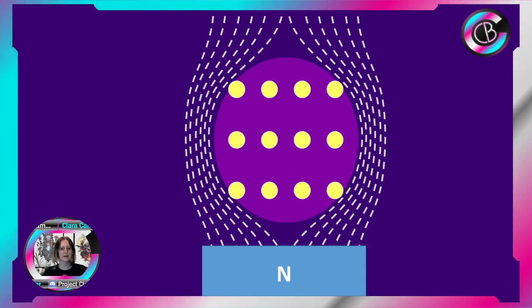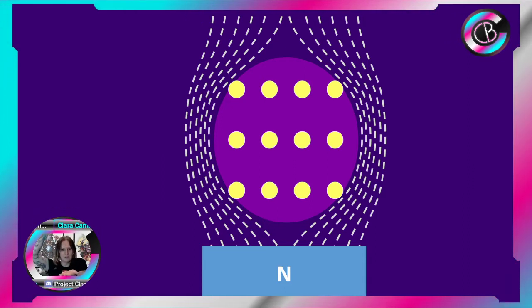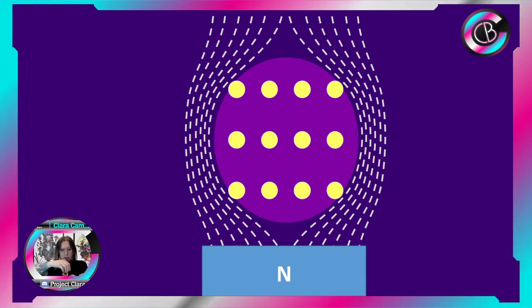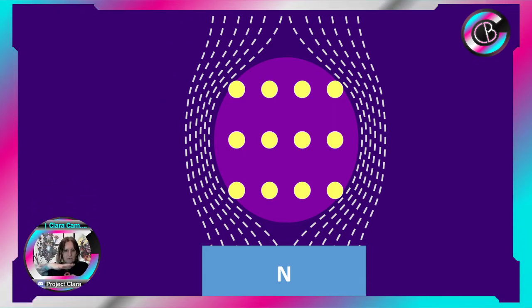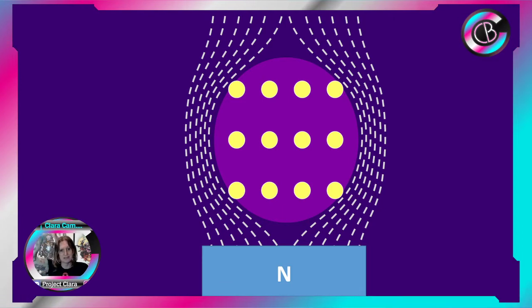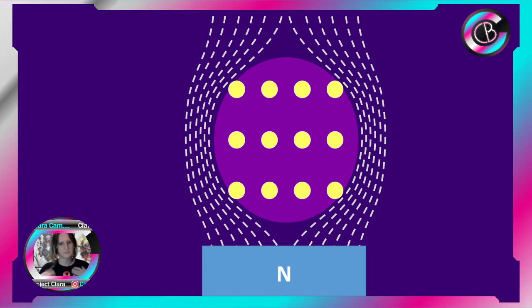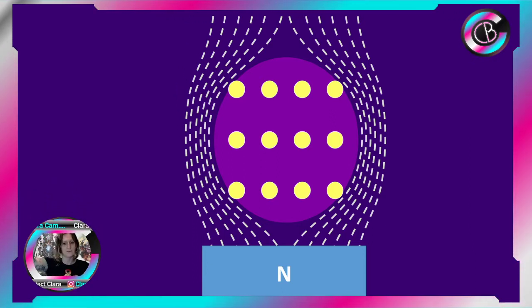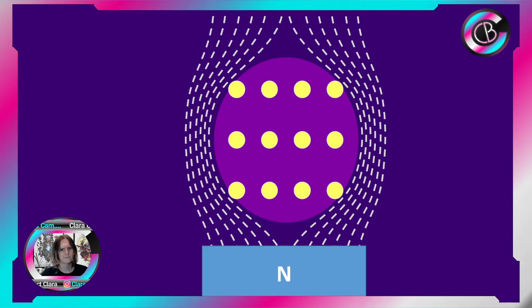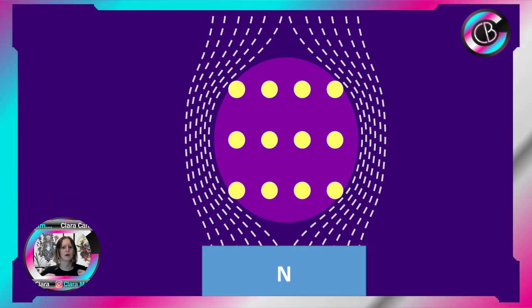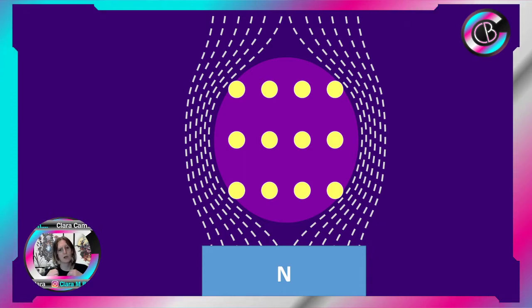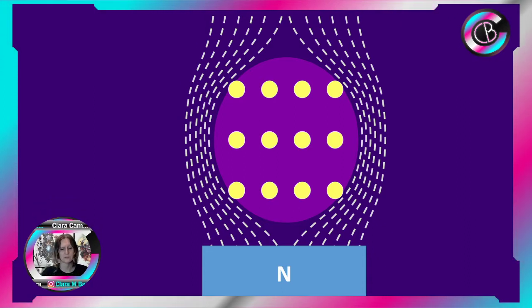So if you imagine that you had a permanent magnet and you dropped a cooled superconductor on it, it would sort of levitate because there's this force where the magnetic field lines are bending out of the way, and so it's not a repulsion per se, it's just that it can't move through. And this is what happens with classic superconductors, which we call type 1 superconductors.